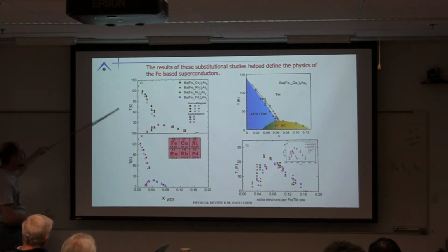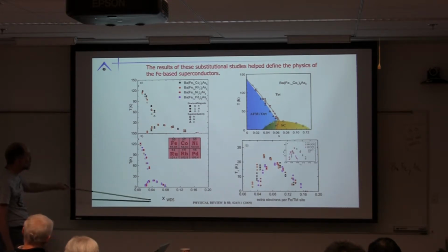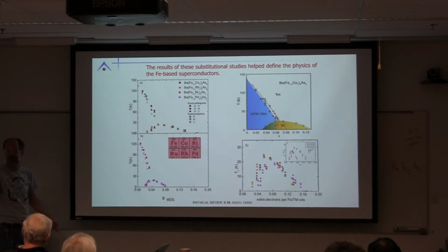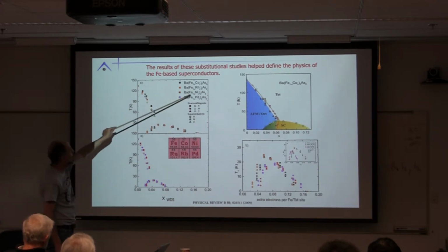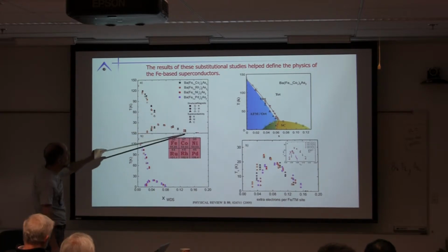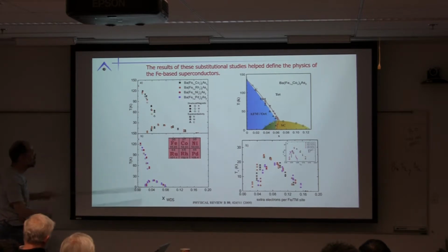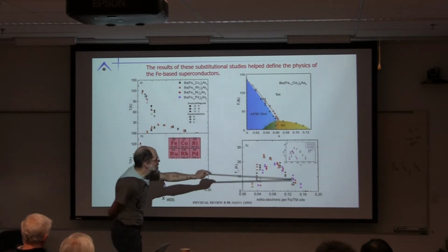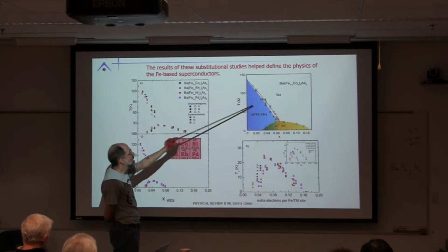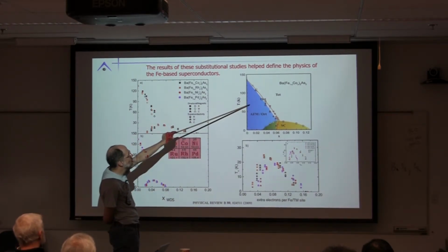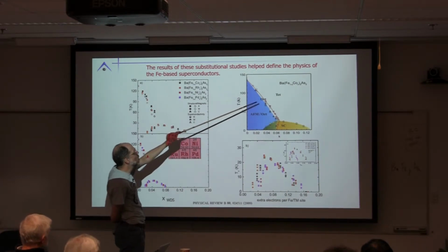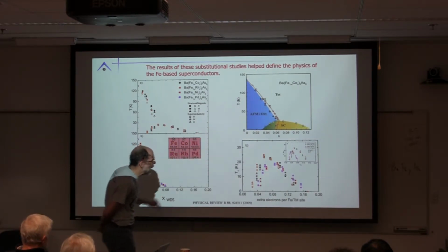We could now make physicists' phase diagrams, not materials scientists' phase diagrams, of temperature and composition, but temperature and, well, composition is the same type of thing, it's just different temperatures. We're talking about transition temperatures, magnetic, structural and superconductivity. As we substitute in cobalt, rhodium, nickel, palladium, we can see for isoelectronic substitution we have virtually the same phase diagram. If we shift over one, the phase diagram is scaled by a factor of 2. The TC dome scales with the number of extra electrons, and we could come up with what is really the iconic phase diagram or map for how the structural and magnetic phases interact with each other.